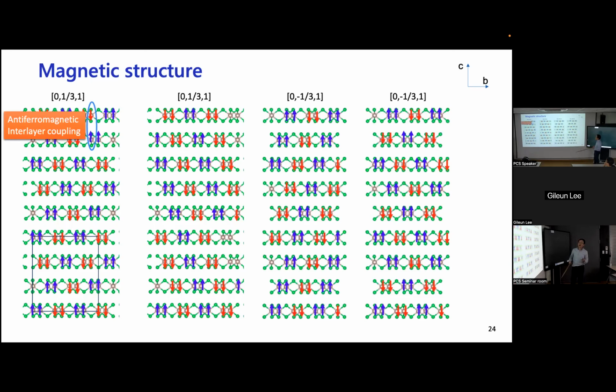But if we were to have actually another type of stacking twin, then you will actually have this type of thing. The reason why this is important is basically this actually determines what kind of interlayer coupling you can get, right? So the difference between this and this is that going directly from this spin to this spin, this has a ferromagnetic interaction, but this one has antiferromagnetic interaction. So distinguishing between these tells us that the interlayer coupling should be antiferromagnetic rather than ferromagnetic. And that is what we have found here.